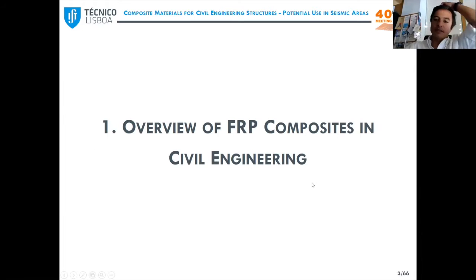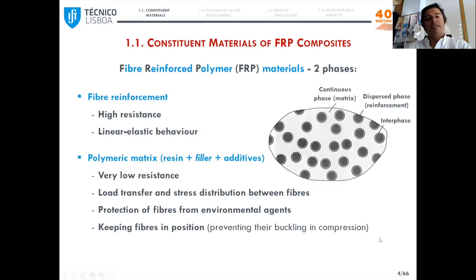So starting with the overview of FRP composites, these materials are basically constituted by 2 phases: the fiber reinforcement, which has high strength and linear elastic behavior, and this would raise a red flag for earthquake engineering, and also the polymeric matrix, which includes resin and usually also filler and additives. Well, the matrix has much lower strength than the fibers, but on the other hand, it has 3 very important functions: load transfer and stress distribution between the fibers, their protection from environmental agents, and also keeping them in position, namely when they are loaded in compression.